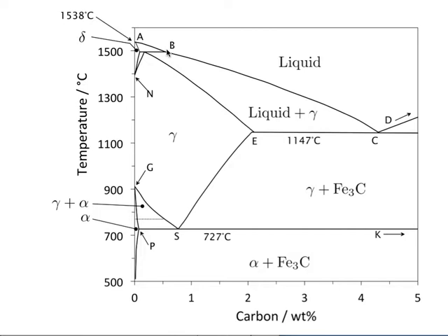Now, the reason for this is magnetism. So magnetism stabilizes the alpha once again when you get down to low temperatures. It's a very large term in the free energy difference between the austenite and ferrite. Now, in the silicon-rich TRIP-assisted steels, we had about 70% of allotriomorphic ferrite, right?